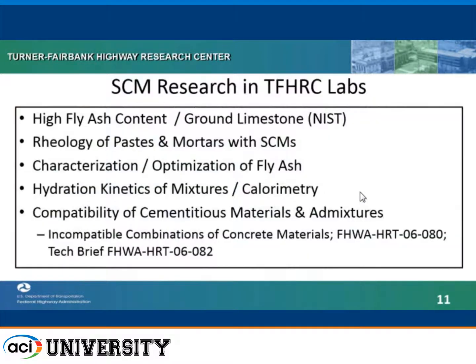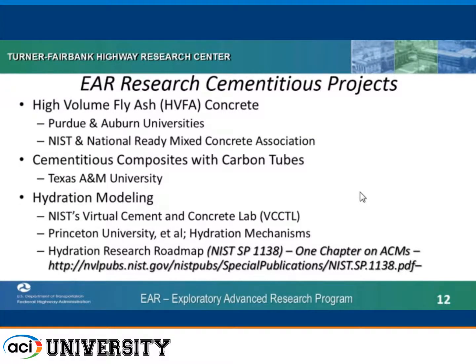In terms of the research that we're doing at the Turner Fairbank Highway Research Center, we are taking a look at higher fly ash content. We're working with NIST on using more ground limestone with Portland cement. We're looking at rheology of pastes and mortars with these different materials, characterizing and optimizing fly ash. We have the capability of looking at the calorimetry and the kinetics. And there is some previous work that was done by Peter Taylor on the compatibility of cementitious materials with admixtures, which addresses various tests that might be used to look at particular cements with particular admixtures as well.